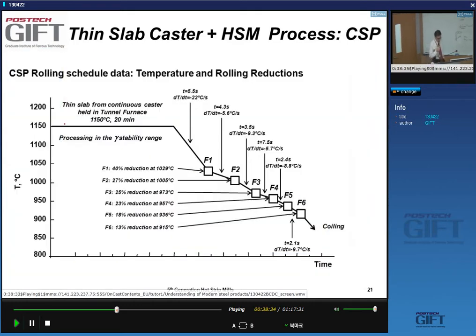Right, and so here you have some detailed numbers of what's happening with the finishers. It's interesting to look at the process as you do the rolling. So we have our thin slab, 1150 for 20 minutes in the furnace, yes? And then you cool down to around 1000 degrees C, yes?